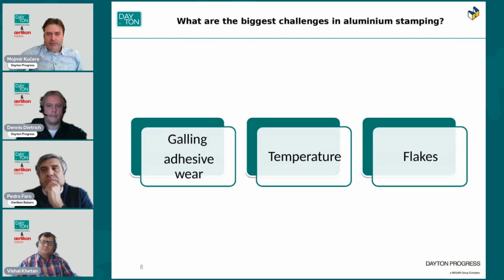Okay. So now we will probably speak about the biggest challenges in aluminum stamping. This is right, Dennis? Yeah. The biggest challenge when punching aluminium is the forming of a build-up edge on the punch, which is also known as punch galling or adhesive wear. This build-up edge becomes stronger the higher the temperature rises during the work process. As soon as the build-up edge has formed, flakes will be created, which can then pose a problem for the tool and the finished part.